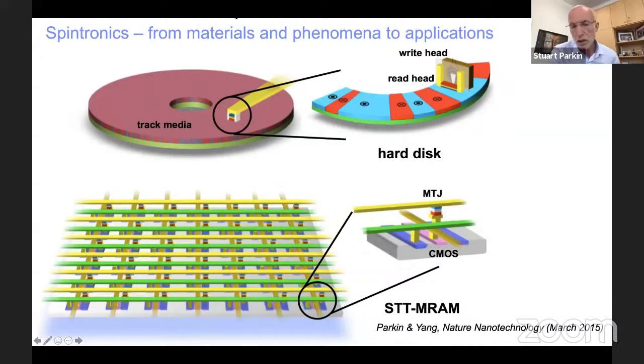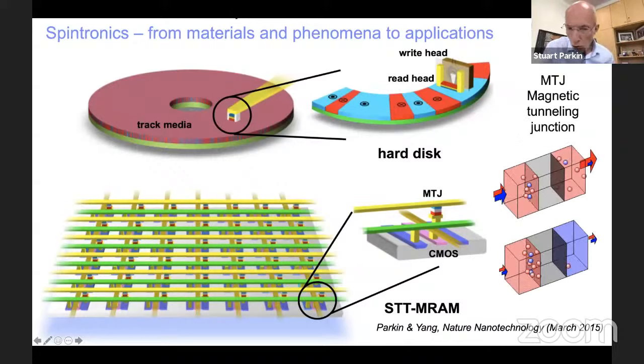And this spin valve sensor was basically a sandwich of two magnetic layers separated by a metallic layer, and the physics involved was that of giant magnetoresistance, spin-dependent scattering. But the same structure and all of the spin engineering phenomenon that we used to create it is now involved in a similar structure, a magnetic tunneling junction, and you can see this in this cartoon. The pink and red layers on the right-hand side correspond to magnetic layers, typically perpendicularly magnetized, and the gray layer is an insulating layer. The electrons tunnel from one magnetic layer to the other, and the tunneling is strongly dependent on the spin of the electron via both the tunneling matrix elements through the tunnel barrier, as well as the spin-dependent density of states within the respective electrodes.